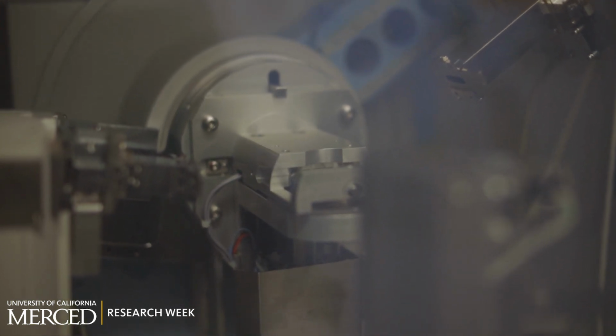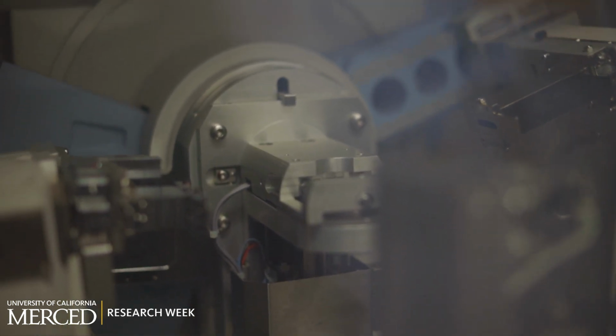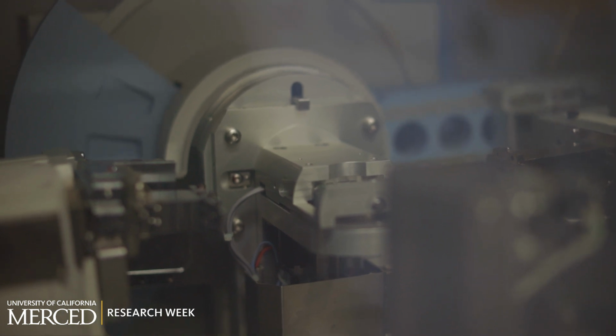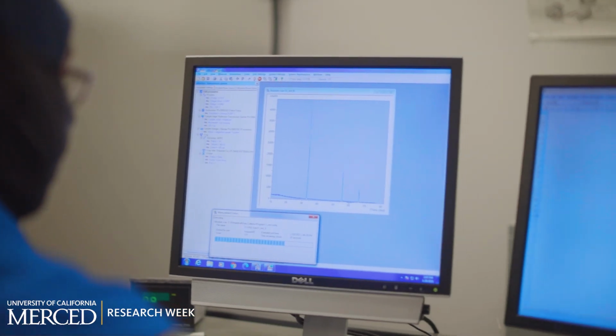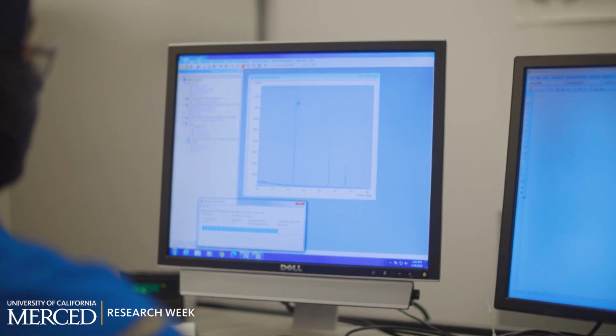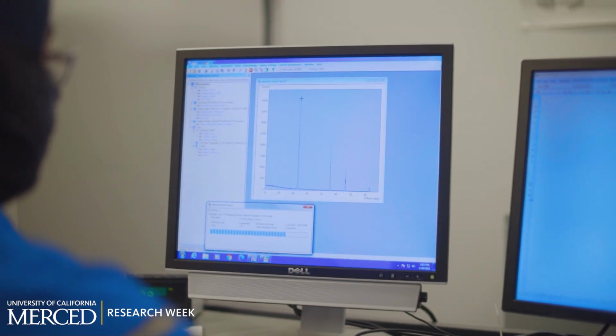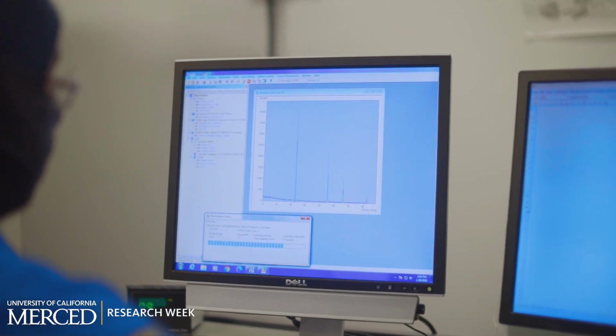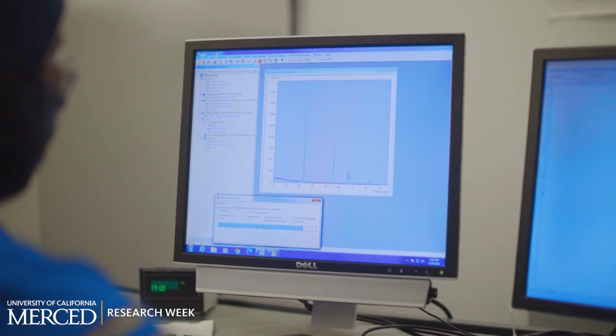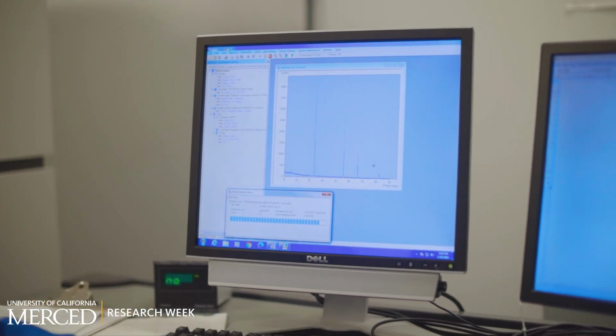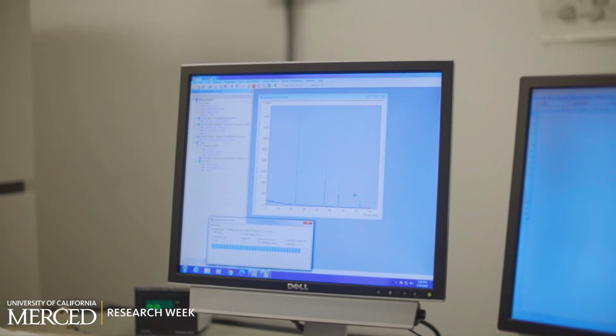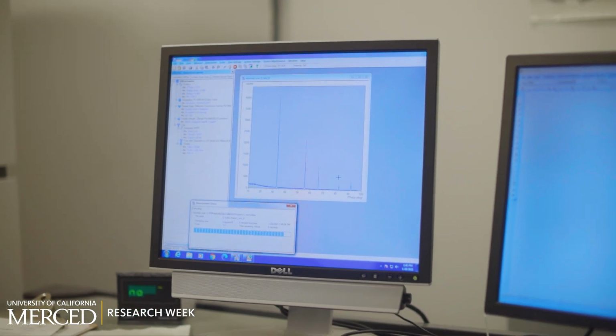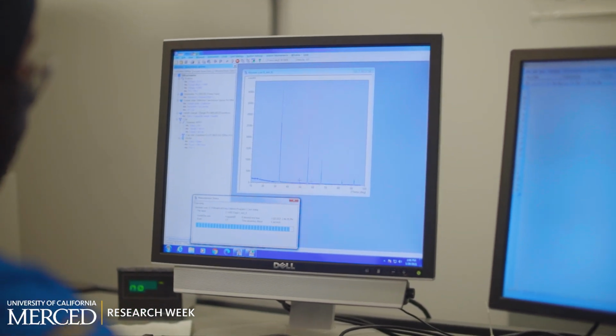As you can see, the arms are moving. And then we'll get a corresponding spectrum, 35, 55. At these different angles, we see diffraction occurring. So this is basically the fingerprint of the crystal structure of the material, or the silicon wafer that I put inside the chamber there.